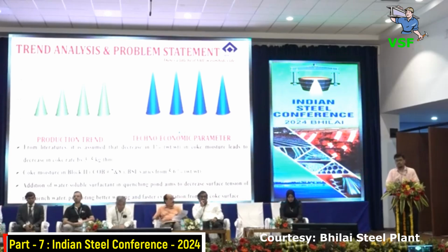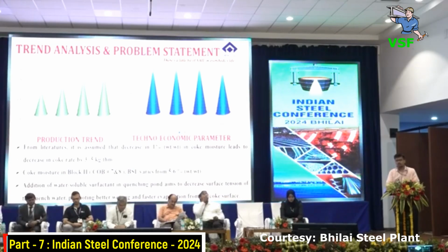metal production. So there are several parameters in which coke rate can be controlled, and RDCIS selected one parameter, that was coke moisture. As per literatures, it is assumed that decrease in 1% in coke moisture leads to decrease in coke rate by 3 to 5 kg per ton of hot metal. In block 2, which comprises of coke oven batteries 7 and 8 in Bokaro Steel Plant, the coke moisture varied from 5 to 6%. The objective of the project was to reduce this coke moisture by around 2%.